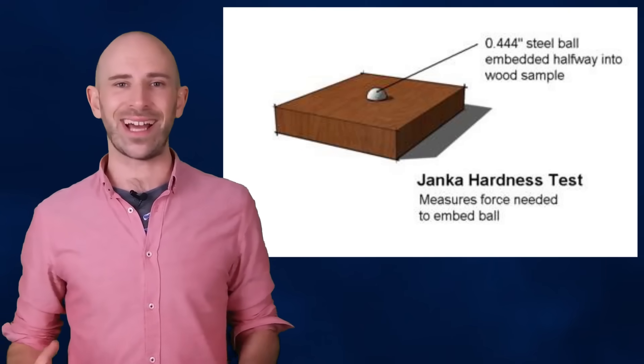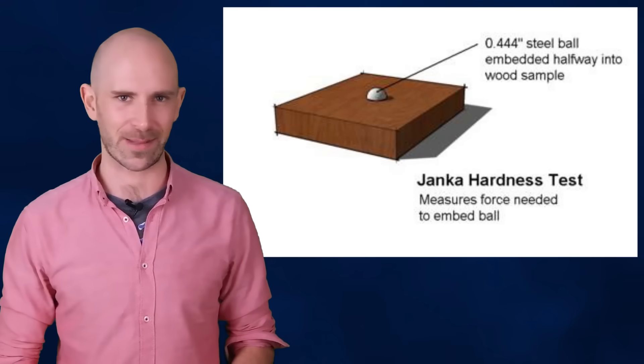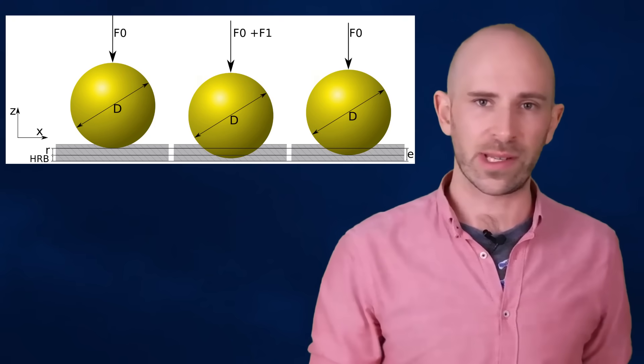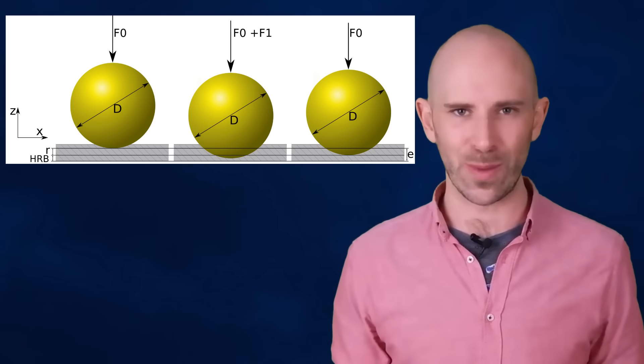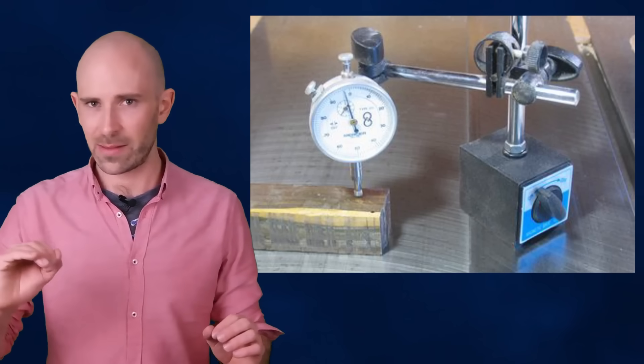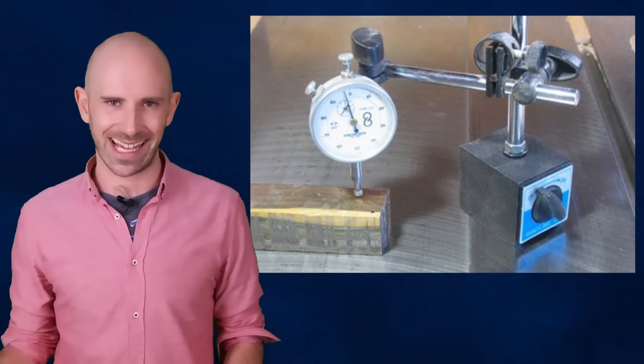Although the terms hardwood and softwood are in no way related to the toughness of a given piece of wood, it is noted that for the most part, hardwoods are usually harder than softwoods. The most common way to measure wood hardness is using something known as the Janka Hardness Test, which has been an industry standard since 1906. This involves measuring the average amount of force required to embed a 0.44-inch steel ball to half its diameter into a type of wood. It is also distinguished via side hardness and end hardness — whether the test was done on the surface of a plank or on the cut surface of the stump. Most of the time, the numbers quoted are referring to side hardness.